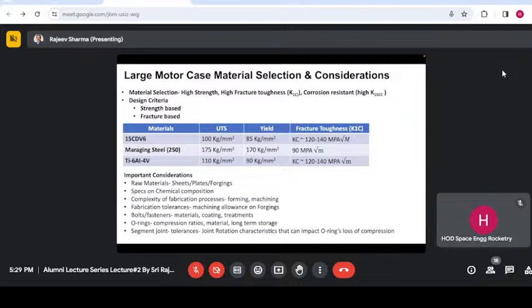And so we had to do a strength-based design, and I had to check for fracture-based design using the fracture toughness. An important consideration was the sheet thicknesses, plates and forgings, and how much forging tolerance. Remember, we had no experience. Mr. Damodar and I had made countless trips to Walchandnagar Industries and other places. The complexity of the tooling and the forming of the domes of the rocket motor, we had used torispherical domes. The material for the fasteners, the size of the bolts. In this case, we were looking at M16, M20 kind of fasteners, and these were fine-pitched fasteners. Fine-pitched fasteners at that size pose their own problem.